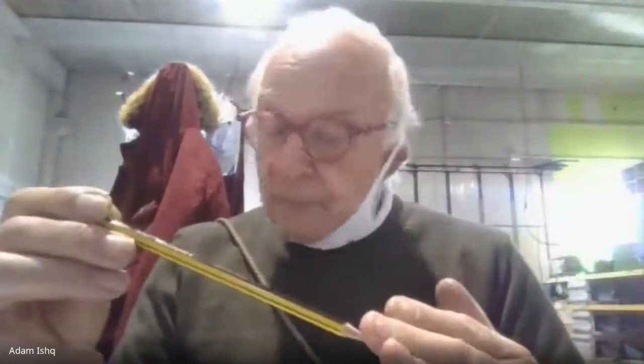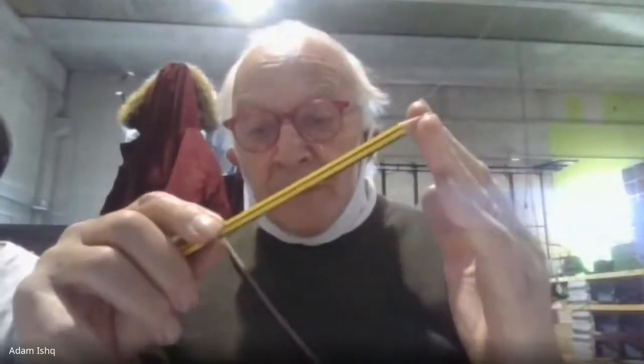If you have perpendicular orientation with ultrasonic, very good signal. If the orientation changes, very bad signal. With time of flight, you don't face this limitation, because time of flight works on the extremity of your defect. That means on the extremity of your crack, on the tip. That means the upper extremity of the crack in the weld is the upper tip. And now I show you with the first image.